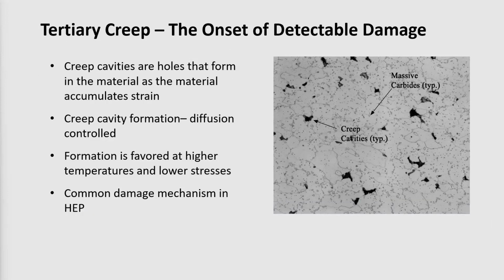Thank you. Now, in terms of creep damage, we said that creep is time-dependent damage that will gradually accelerate, assuming that a constant stress is maintained. And depending upon the temperature and the level of stress that's applied, creep damage can manifest itself in a number of different ways. But for the temperatures and stresses at which these piping systems generally operate, what you will typically see with creep damage is just as is evidenced here.